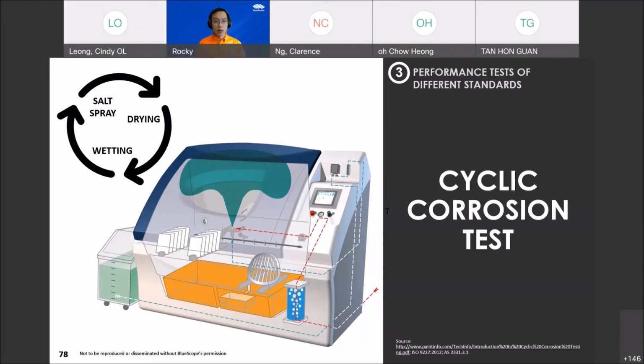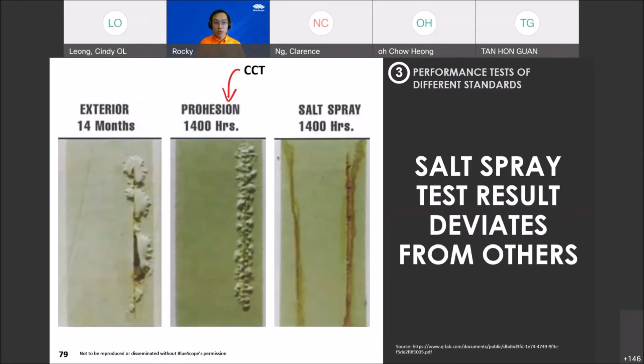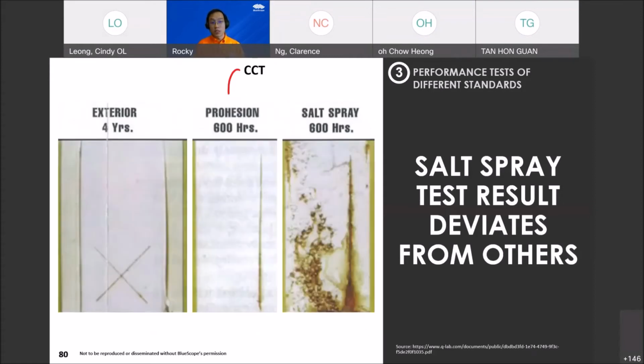there is some data that compares salt spray and cyclic corrosion with the outdoor exposure, and this is how it looks, right? So Prohesion, as you can see here, is actually a type of cyclic corrosion test, and exterior means outdoor exposure test, right? So left is outdoor exposure, Prohesion is cyclic corrosion, and salt spray is on the right. And what you can see here is that the salt spray test seems to show some sign of rust, okay, but it deviates from the results shown in the outdoor exposure, only 14 months. Yeah. If this is not enough, there's another result where the salt spray test of 600 hours actually is worse off when compared to the outdoor exposure of 4 years, right? Compared to cyclic corrosion, which seems not very severe.